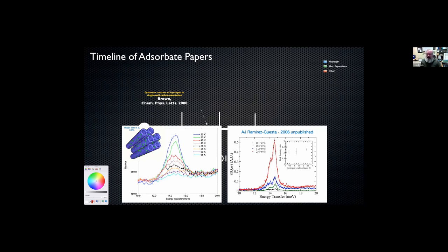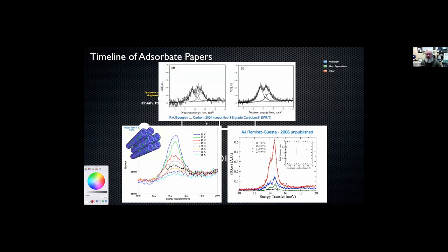We didn't know at that time the origin of those rotations. We suspected it could be just the hydrogen manifold, the J=1 level, splitting into two states with MJ 0 and MJ ±1. So you always get this constant ratio of two. That disagreed with some other things in the literature that showed even more complex patterns.